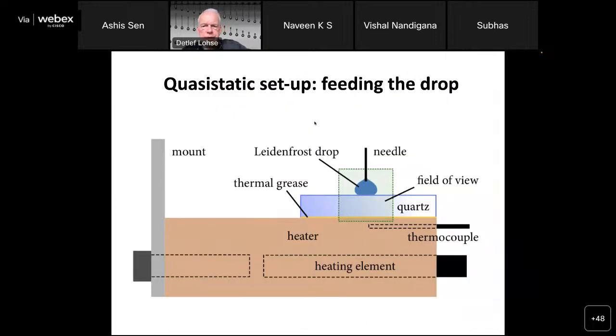So here you see the setup with this trick of Michiel to put this droplet close to a needle. And this needle has two functions. First of all, it avoids that this droplet is wiggling back and forth. And second, it feeds the droplet so that the evaporation loss is compensated.